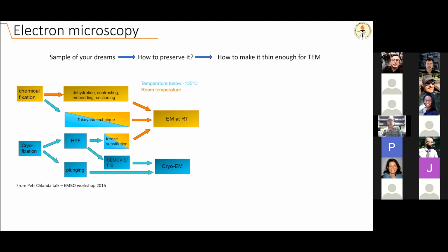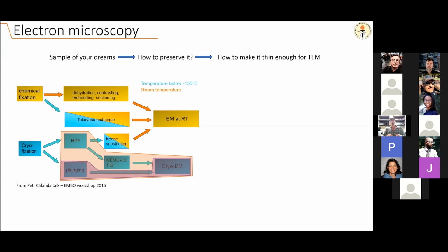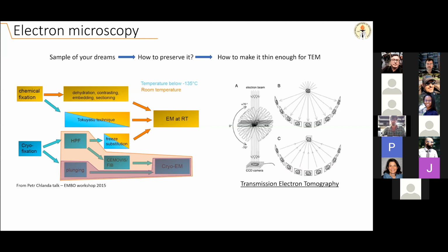So by how to preserve it, it means how to achieve successful vitrification of our sample. Liza very well explained the principles and what you should care about when you're plunge freezing. And usually samples that can be plunge frozen can be directly observed by cryo-electron microscopy. So it's a two-step process. But unfortunately, when we're interested in samples that are above a certain range, we need to resort to thinning methods.